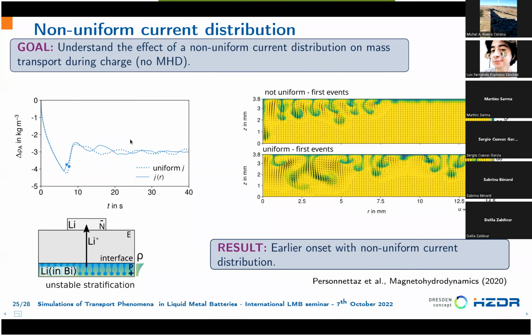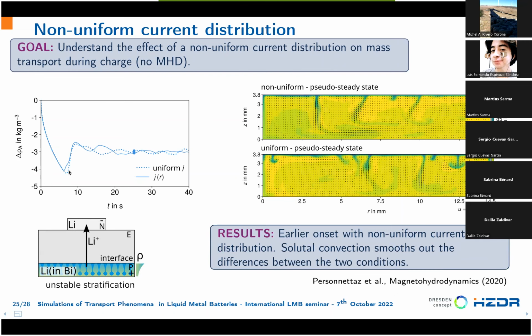And what is taking place during charge is slightly different. So during charge, we have solutal convection, and solutal convection starts earlier in the center of the electrode, because there we remove lithium more efficiently. So we have some difference at the beginning. The onset takes place earlier in the non-uniform current case than in the uniform, as we also see from this evolution of the concentration difference. But later in the steady state condition, solutal convection is able to smooth out all the differences that the non-uniform current distribution is leading to.